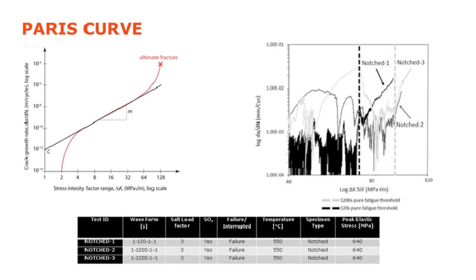So if we have a look then at our three results plotted on the Paris curve, the plot on the right here, and start looking at notch 1, to the left of what I've put in there as a threshold line, we see there's very little or no relationship really between stress intensity factor and dA/dN early on in the crack growth. Our crack propagation is driven really more by time-dependent or corrosion-driven factors rather than stress intensity factor.